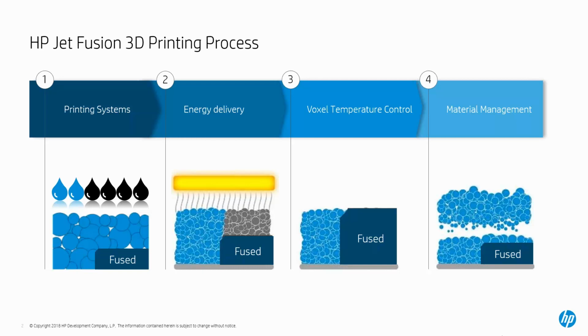And in between each pass, we cover each layer with nylon powder. As I said before, that repeats itself and the bed lowers, and then you're left with a fused part. So just quickly as we go from the left, we disperse the agents. We follow that with infrared energy. The bed lowers, where the agents are applied, you have the fused part, and then we cover that with powder, and then so on and so on.